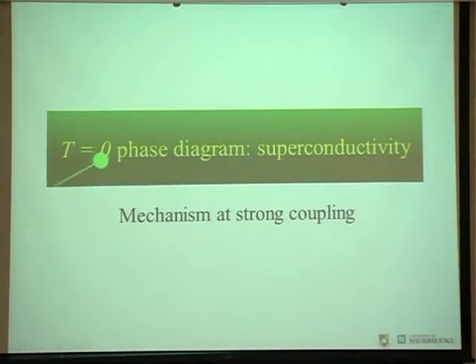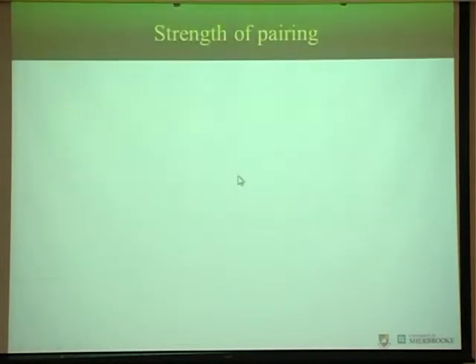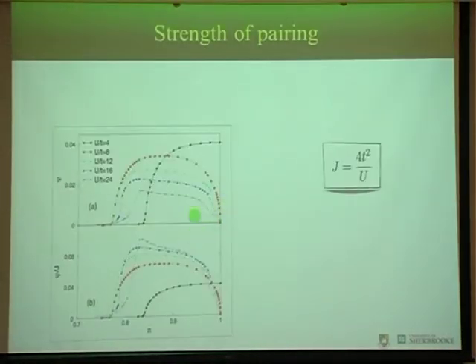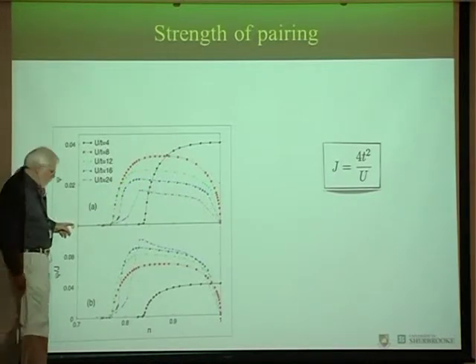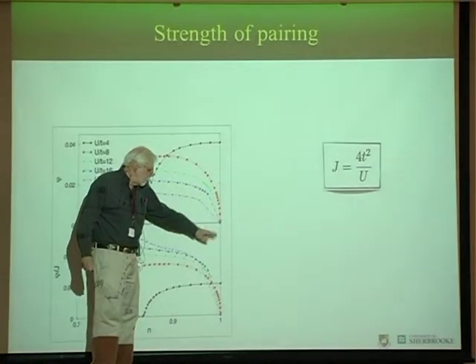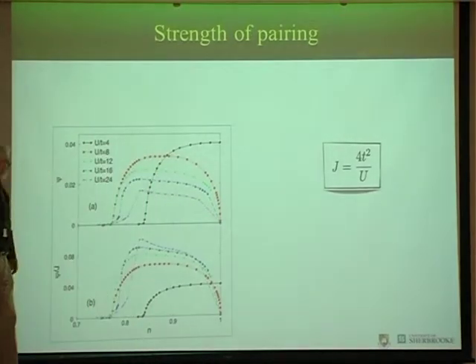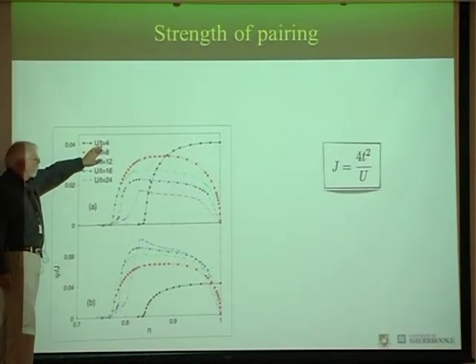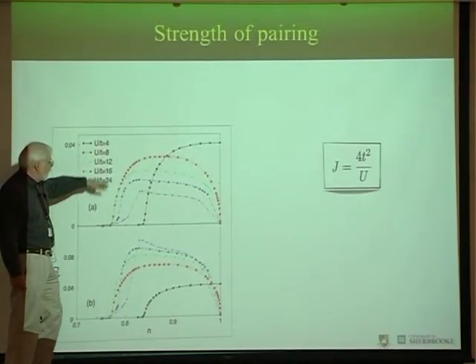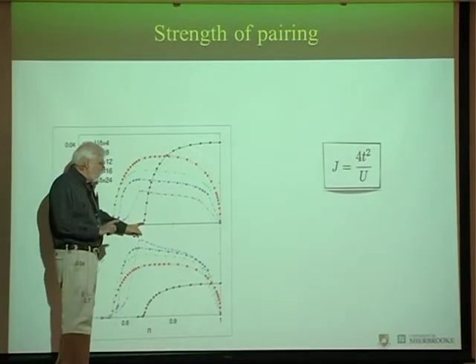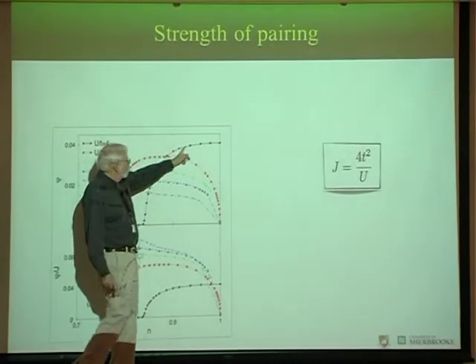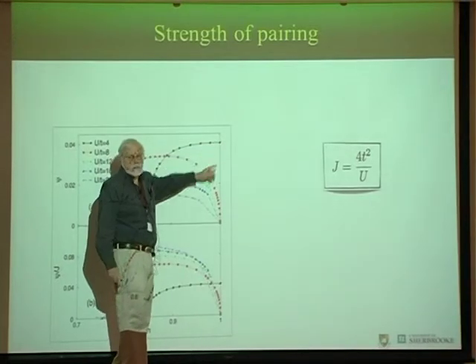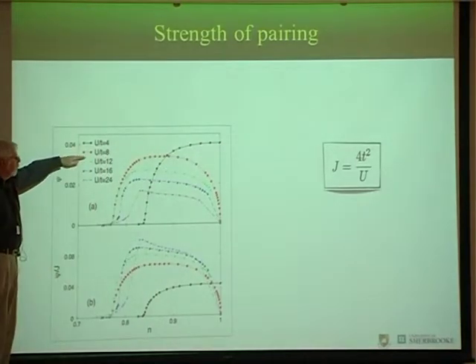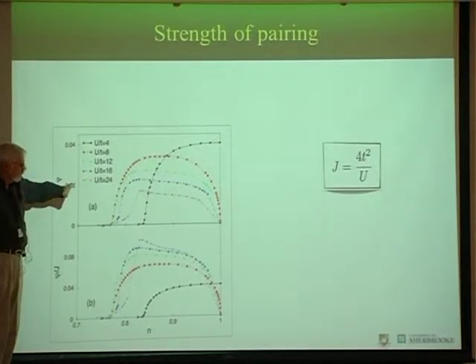Okay. So what is the pairing mechanism at strong coupling? Well, if we just look at the value of the order parameter, this is a plot of the order parameter as a function of filling. So half filling is here, is 1. And if you're not in the Mott insulator at half filling, so U is half the bandwidth here, if you don't allow for antiferromagnetism, you see that the order parameter goes up all the way to half filling.